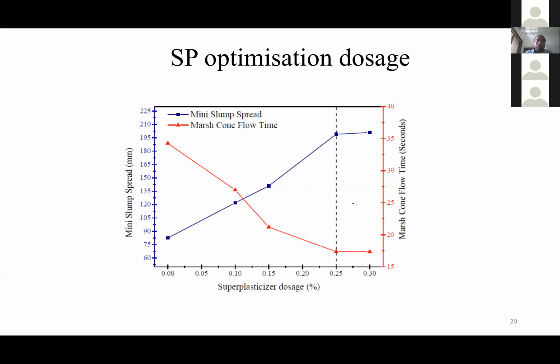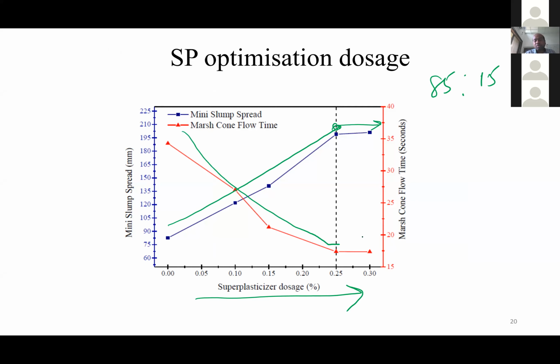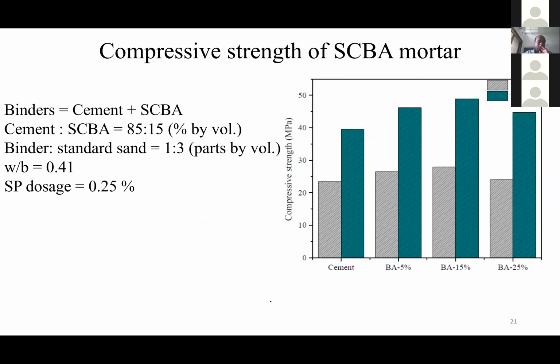So to do the test with increase in SP dosage for this 85% OPC and 15% SCBA, the PCE based SP dosage is increased, and you could clearly see that the mini-slump flow increased, and beyond this one, there is not much of an increment. The same thing with marsh cone, the time decreased, beyond this one, not much change. So this 0.25% SP dosage is the optimized dosage for this particular system.